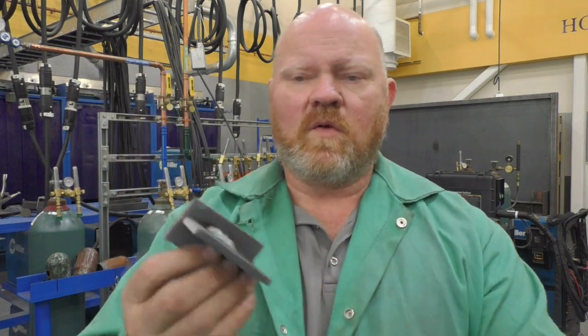What do you do when you're at home? Okay. Well, these are runoff tabs we use on the ends of groove welds. These are quarter inch plate, inch and a half by three. And I've got two of them here that I welded up. And I only welded about an inch. So if I'm at home, I don't have 3/8 plate. I don't have a hydraulic bending machine. And even if I had the 3/8 plate and I made the weld, the reality is that I could be all day outside with a sledgehammer trying to break that weld and not do it, okay?